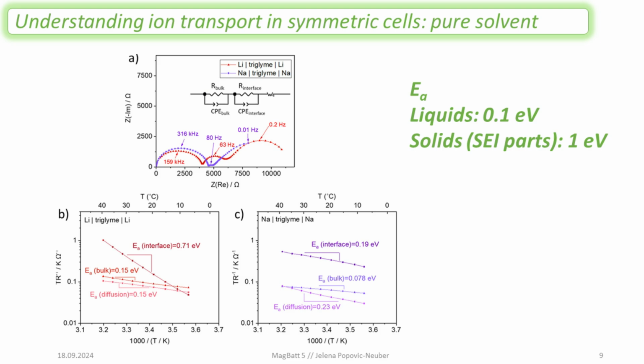This is a very similar type of data that Aurbach also saw in the mid-90s. His conclusion after seeing this data was, well, this has to be a relatively dense SEI, but that SEI seems to be more conductive than its ingredients. Why is that so? Since we could not directly measure it, he had to start to speculate. He speculated a couple of things, one being space charge zones at the grains of these specific compounds. So there are, for whichever reason, high conducting pathways in the space charge zone, or amorphicity, and for whichever reason, amorphous materials are more conductive.